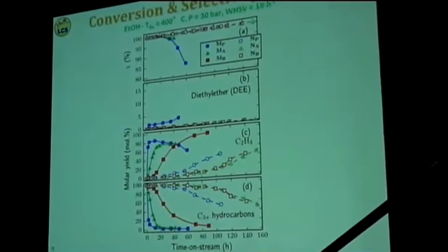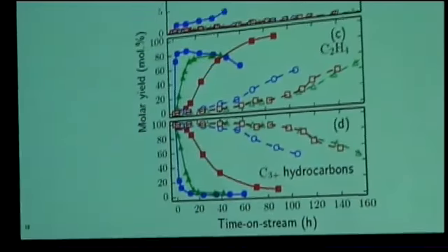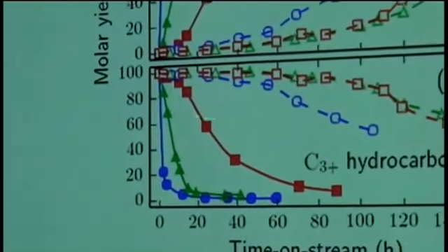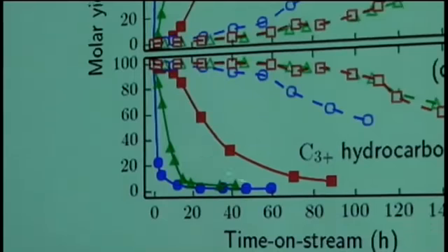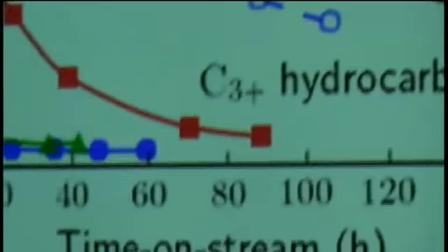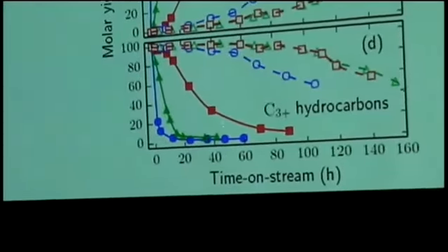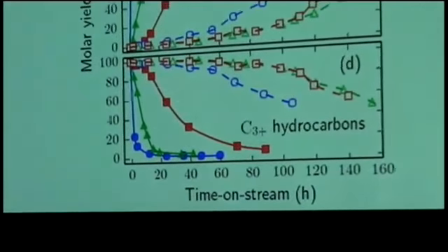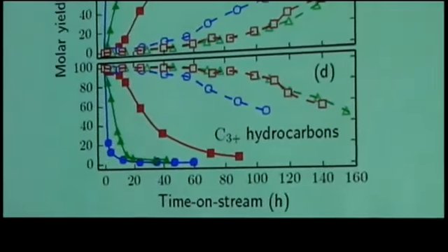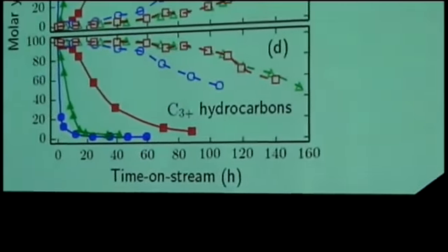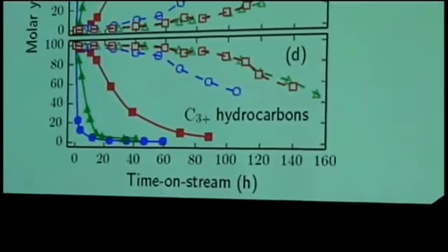If you look at the product distribution, the hydrocarbons that are heavier than C3, so without ethylene, you see two families of catalysts that are emerging. The first family is these filled symbols, and these are materials coming from the micron-sized zeolites. So this is the parent. The green one is the material that has some macropore, and this is the material that has been treated with a caustic solution that contains a substantial proportion of mesopores. And you see that hierarchization by post-treatment is quite effective in giving you some improved performance.